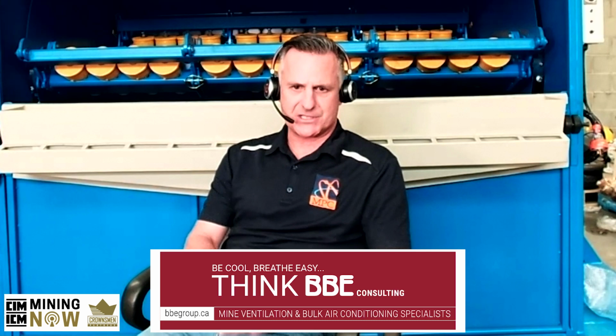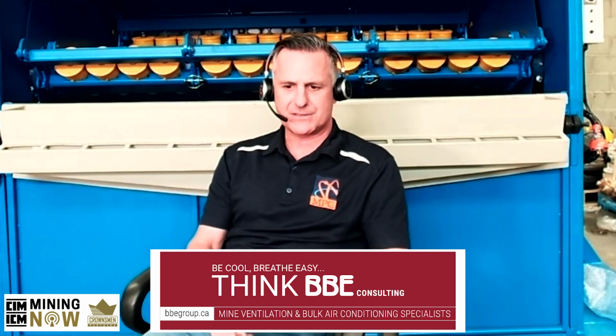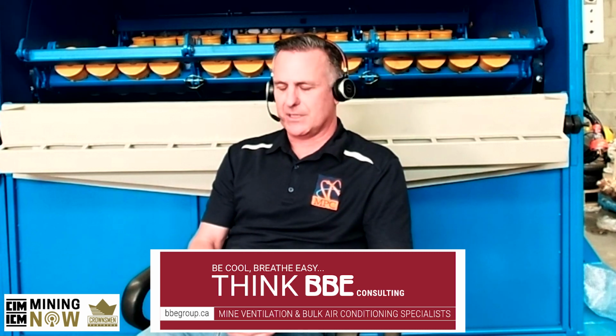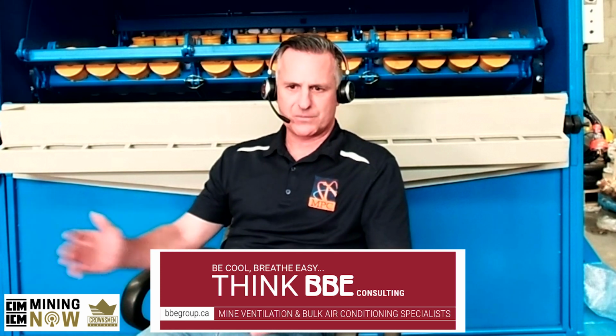Okay, so LeachWELL is the chemical which is the cyanide accelerant. That speeds up the cyanidation reaction. Now, back to what you were saying in regards to being used in Knelson concentrators. That's coarse gold recovery, part of the milling circuit of a gold mine. You can recover coarse gold, particulate type, quite nuggety gold, prior to going through the leaching process. If you can physically remove it through gravity means, like Knelson concentrators as the example, then you can avoid going through that whole leaching process.